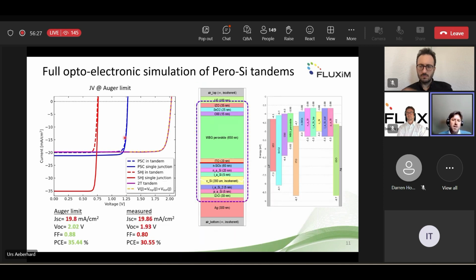And then we can compare these subcell characteristics with the full tandem characteristic, for instance, by just adding the subcell or the filtered subcell JV curves. In this case, we see that it's a perfect match. So there are actually no losses that incur from connecting the device in series. So it's quite an ideal situation. Well, this is at the Auger limit. So this is as good as it gets, including transport.